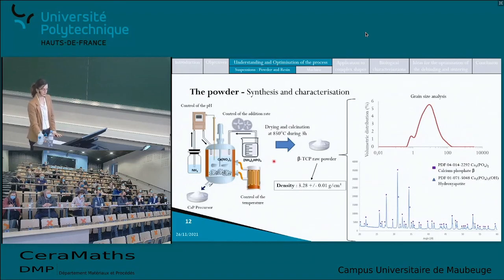I did some grain size analysis of this powder, and I obtained a very wide grain size distribution. And I also did some XRD analysis on the powder in order to attest its composition. And I realized that two phases were present. The beta-TCP phase is mostly present in the powder, but there is also a slight bit of hydroxyapatite, which was not a problem for the application targeted.